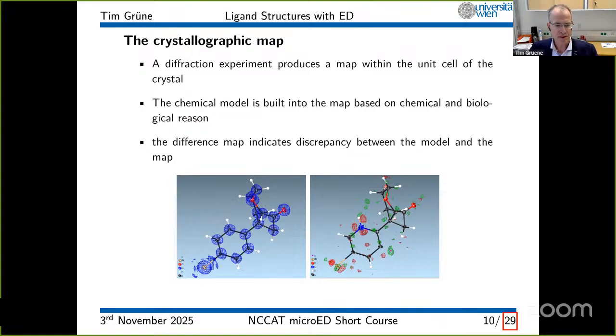The blob that you see here, that's a bromine atom. Bromine is very, very heavy, and especially in X-ray crystallography, the data need to be corrected during scaling. Absorption correction is very important, and for heavy atoms, that's not always perfectly possible. So the difference that we see here is not because the model is wrong, but because the independent atom model that we use for refinement most of the time has got its limits, and the data in this case are better than the chemical model.